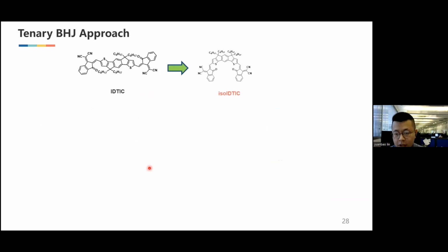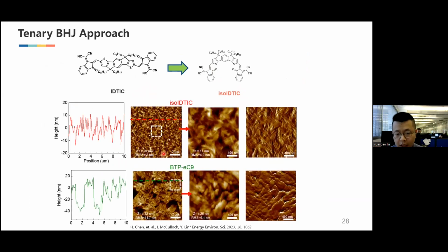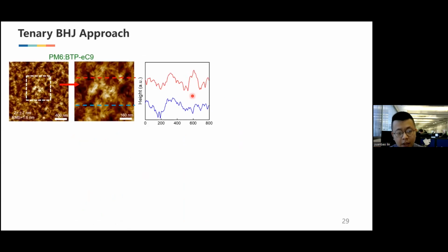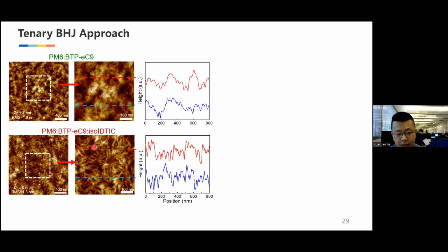So we synthesized the iso-IDTIC, and after testing with AFM, we can see a very clear fibrous structure. But if we test BTP-eC9, because the Y-series acceptors degrade very easily after annealing, we cannot see the fibrous structure in BTP-eC9. So we tried putting this iso-IDTIC as the third component in the PM6:BTP-eC9 system. For PM6:BTP-eC9, we can see the fibrous structure, but with the iso-IDTIC, this fibrous structure is more clear, sharper and more distinct.